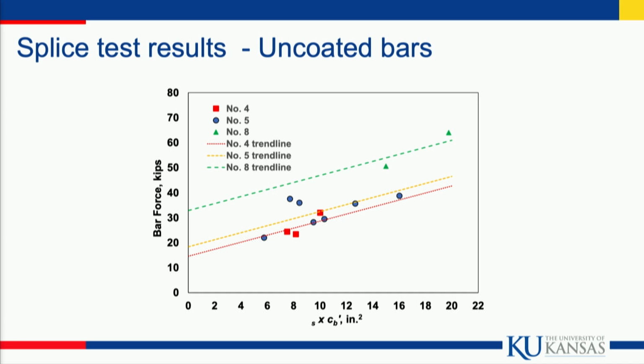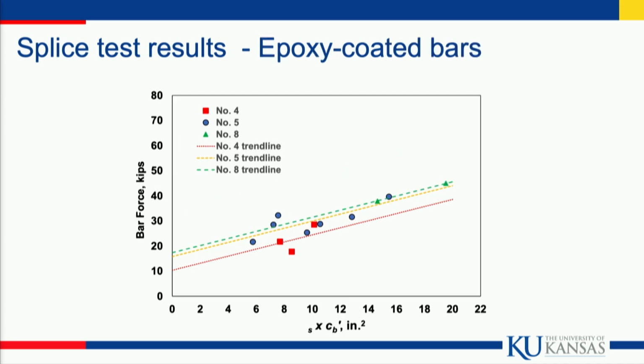How about the coated bars, epoxy-coated bars? Similar relationship. Interestingly, the slopes on the 2 figures are identical to 3 significant figures. Here, there's not nearly as much spread between the number 8 bars and the smaller bars, but these lines are all lower with epoxy-coated bars, so they're not that strong.